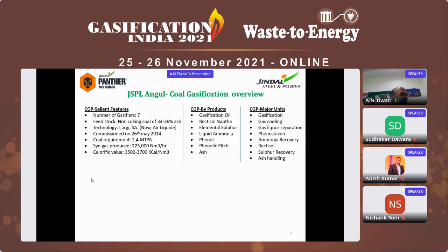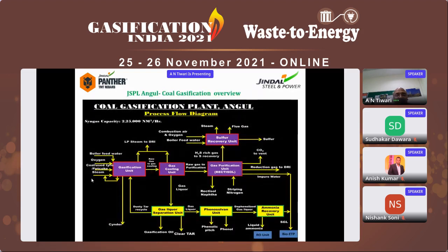The major units in the coal gasification plants are gasification unit, gas cooling, gas liquor separation, Phenosolvan, ammonia recovery, rectisol, sulfur recovery, and ash handling. If you see the block diagram, we have the gasification unit. Gas is coming from the gasification unit, goes to the gas cooling, then it goes to the acid gas removal, where we are removing all the impurities. Then H2S and COS goes to the sulfur recovery. And the reduction gas, which mainly contains around 52-53% of hydrogen, 32 to 34% of carbon monoxide, and around 13% of methane goes to the DRI furnace for the reduction purpose.